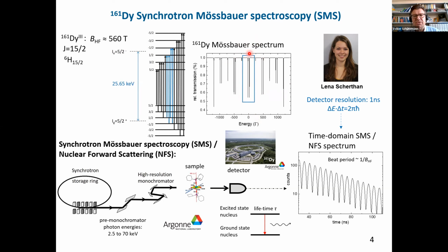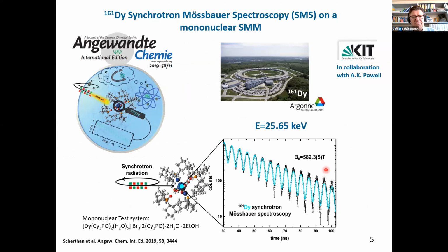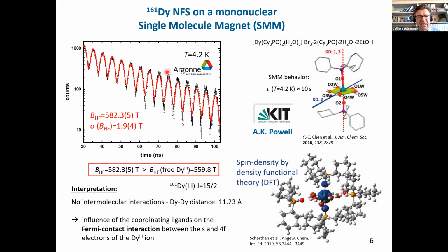However, due to the resolution of the detector, we only see transitions between these lines, or these levels, and that is basically shown here, where we have a typical beat period, which is reciprocal to the hyperfine field. So the beating is a function of the magnetic hyperfine field of the dysprosium. That was successful. This is the complex here, which was prepared by our collaborators in Karlsruhe, the Annie Powell group. And we were very happy that we could get a very nice pattern and deduce the hyperfine field of 582 Tesla, which is much larger than the expected hyperfine field of a free dysprosium ion.